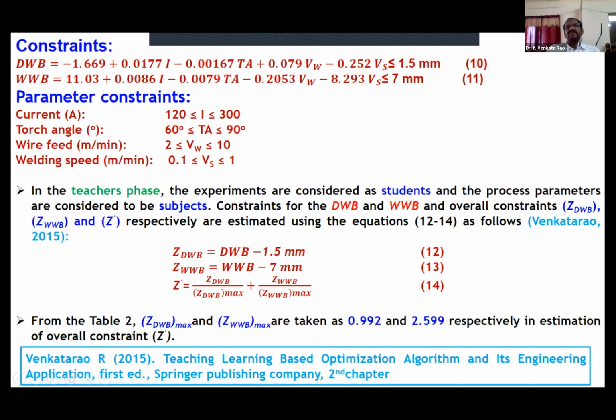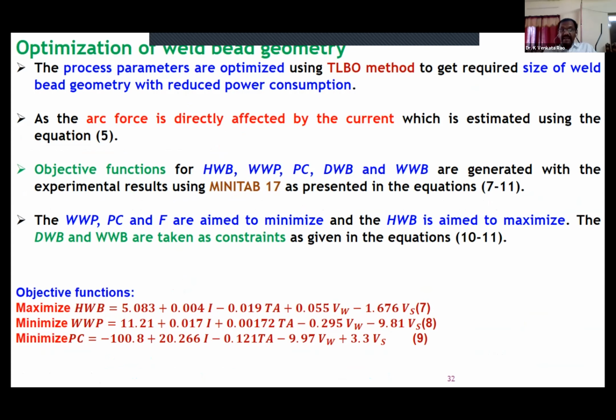Depth of weld bead should not be more than 1.5, always less than 1.5 mm. Width of weld bead should always be less than 7 mm. So we have these constraints. By keeping these constraints in view, we have to optimize the process parameters. All these 5 equations are generated using the experimental data.